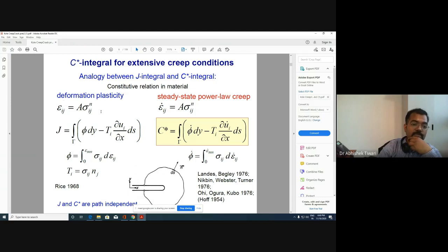There will be an elastic part which will simply follow Hooke's relationship. So epsilon will be equal to sigma divided by Young's modulus. Then we can calculate the J integral. We calculate the J integral experimentally in a different way, but theoretically, it's an integration of the conservative field, which we have discussed earlier. So phi is the strain energy density. T is the traction vector. Traction vector is simply the stress tensor in inner product with the normal vector. The inner product usually reduces the size of the tensor, so it becomes a vector from 3 to 2. And U is the displacement.